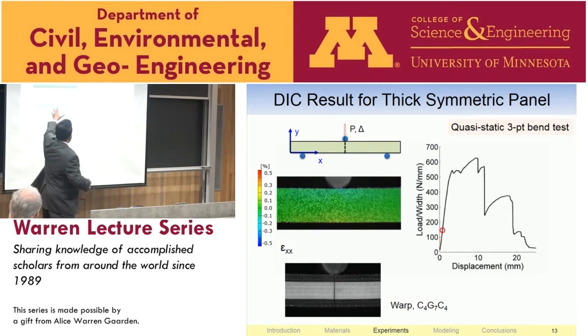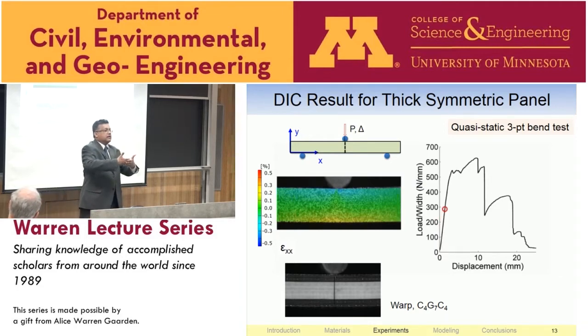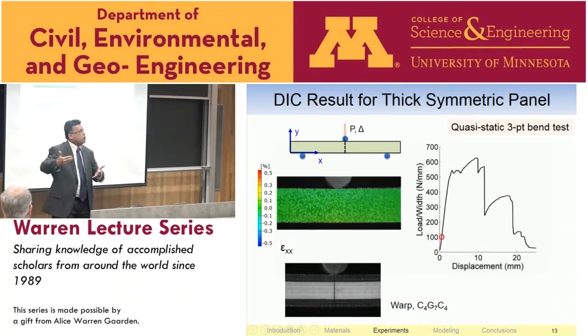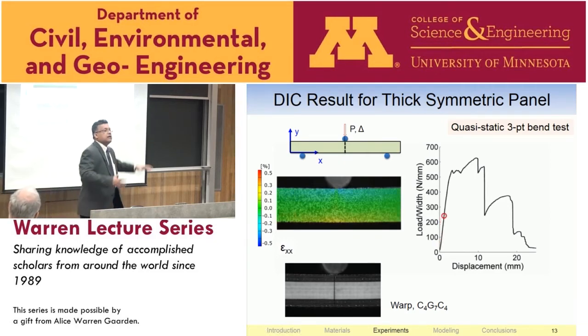And then what happens is that it picks up load again because across the band, loads are still transferred. And so the top layer starts to do what I call multiple kink banding. So you're making use of the material more, right? You want the material to crack, but you don't want it to localize and suddenly rip into two pieces. You want that kink band to absorb a lot of energy, which it does, but then you want to delay complete collapse by getting it to kink more and more. So progressive kinking. So that's what controls that plateau. It keeps going forever, adding this ductility.